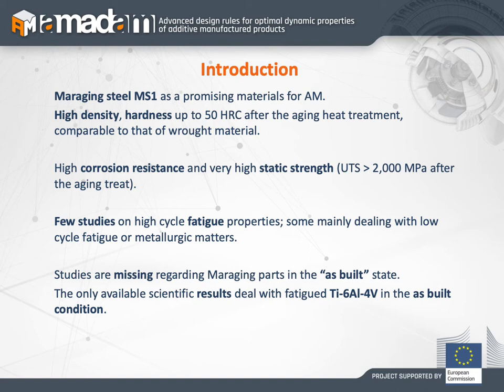application. This material has a high density and hardness up to 50 Rockwell C, and this property is reached after the aging heat treatment. The material has a high corrosion resistance and a very high static strength, so the UTS is greater than 2000 megapascal after the aging treatment. And there are a few studies on high cycle fatigue properties, and particularly